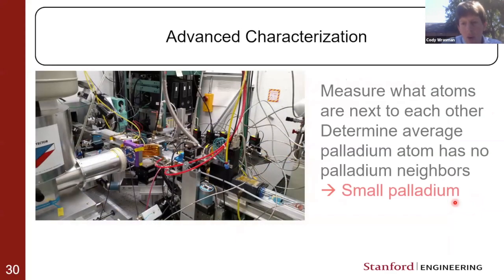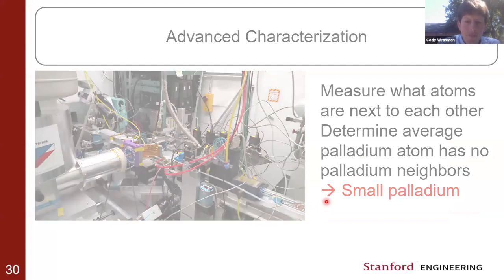I won't get into too many details of these experiments, but basically what we were able to do is determine how many palladium neighbors the average palladium atom has. So in the catalyst that we wanted, all palladium atoms to have no palladium neighbors. And we were actually able to use this technique and determine that we did have those single atoms of palladium kind of located inside of these gold nanoparticles. So we were able to make the catalyst that we wanted.